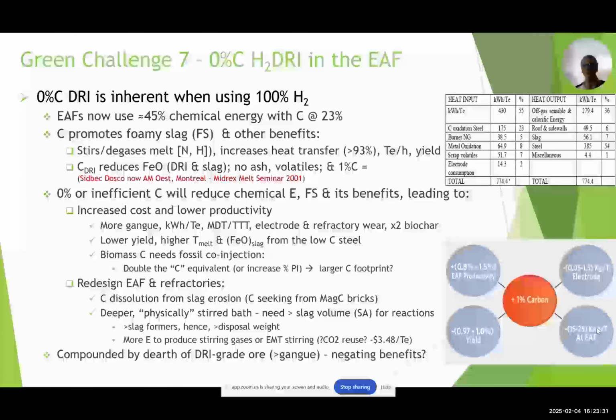Challenge number 7 is zero carbon hydrogen DRI in the EAF, which is inherent when you use 100% hydrogen. The EAFs now, as you can see from the chart here, use 55% electrical and the rest is chemical energy, with carbon being 23%. Carbon foams the slag, gives you a larger surface area. It enables degassing of the melt, nitrogen and hydrogen, increases heat transfer 93%, and tons per hour yield. It also reduces the FeO not only in the DRI but also in the slag, and it doesn't have any ash or volatiles. On the right-hand side here is something that ArcelorMittal put together quite a while ago, showing the increase in productivity, the reduction in kilowatt hours, the reduction in electrodes, and the increase in yield to almost 1%.